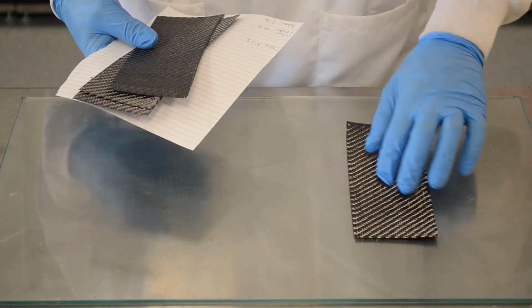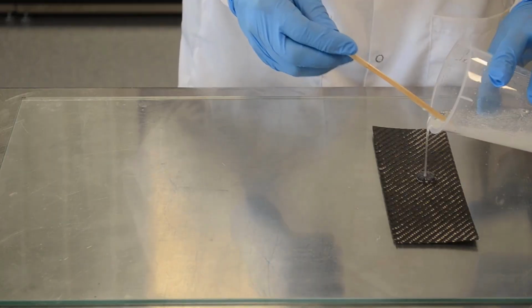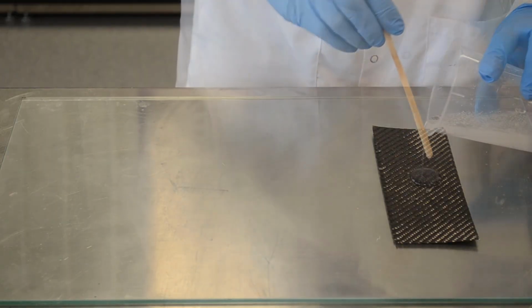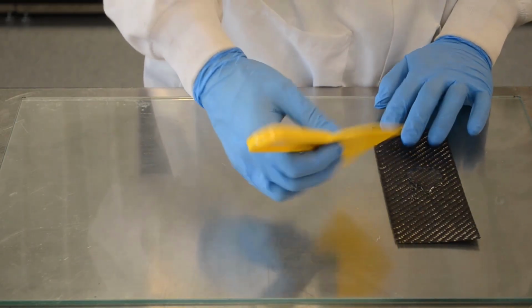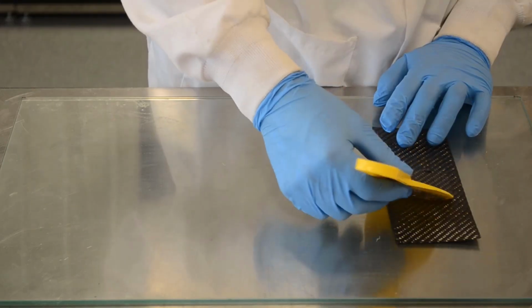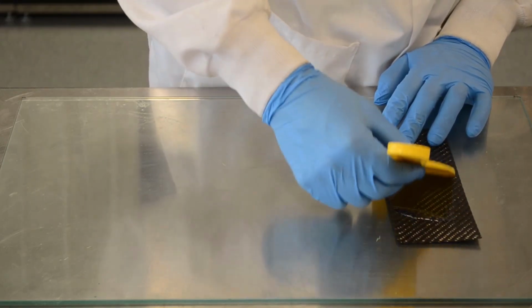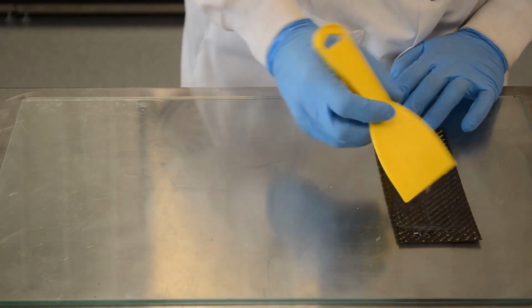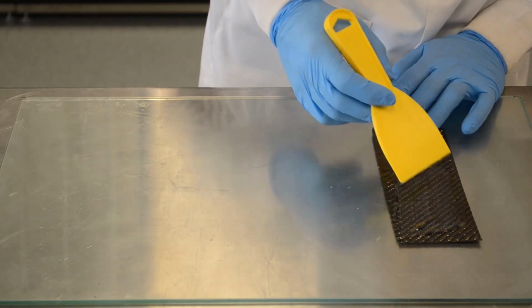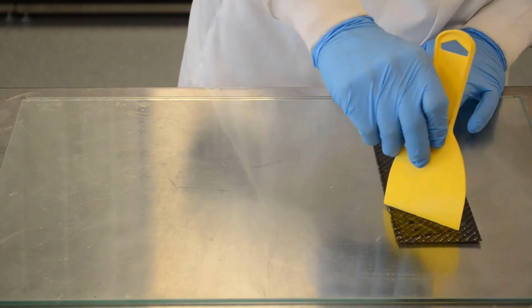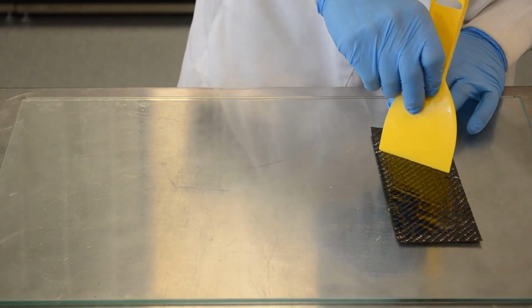During the layup process, 1 ply of fabric is laid on the tool and the resin is evenly applied to the fabric with a plastic paddle. It is important that the tool used to spread the resin does not have any sharp corners that may damage the fabric weave. Ensure that the fabric is fully saturated with resin. If areas are missed, there may be a dry spot in the final part.